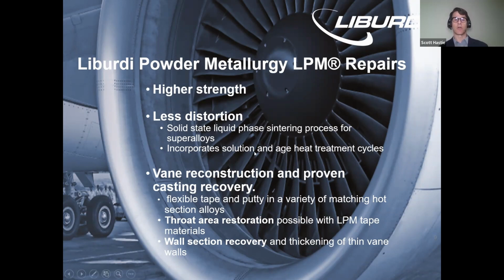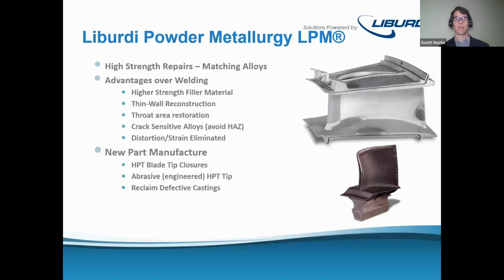So this incorporates both solution and age heat treatment cycles within the process. And so we've been able to do vane reconstruction and even casting recovery. We have both a flexible tape and a putty, which we'll get into a little bit. And then we'll talk about throat area restoration with tape materials, and then wall section recovery and thickening of thin vane walls. So I think the main thing here is we've talked a little bit about these things, but we've even used this in new part manufacture.